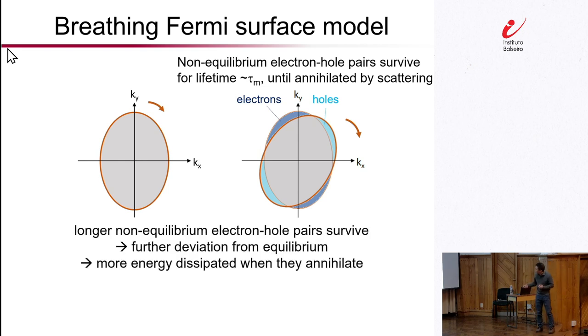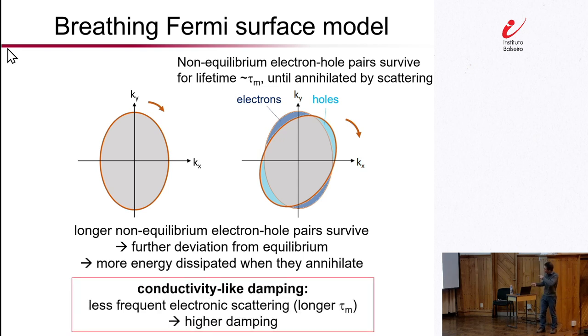Okay, so this is where things get a little strange. The idea here is that the longer these electrons and holes can survive without scattering, they go farther and farther away from equilibrium. So that when they finally annihilate, when they finally recombine via some scattering event, they end up dissipating a larger amount of energy. So that's really the key logic behind the so-called breathing Fermi surface model or conductivity-like damping. So when there's less frequent scattering, these electron and hole pairs get more and more out of equilibrium, so that when they finally scatter, when they finally annihilate, you end up with a higher amount of energy dissipation or damping.